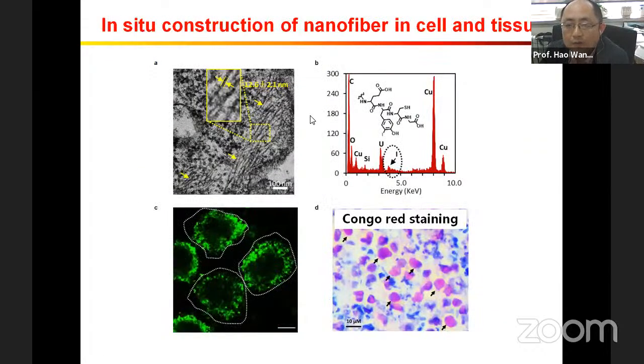And we also found this fibril structure inside of a cell. This is a cell slice, right? And inside of the cell, we found this fibril structure. Before we fed the material, we labeled it with iodine, because the abundance of iodine in the cell is quite low. After labeling our biomolecule with iodine, from EDS we can see very clear signal from iodine, which means this fibril structure comes from our exogenous material. We also used other techniques to stain and confirm this beta sheet structure.